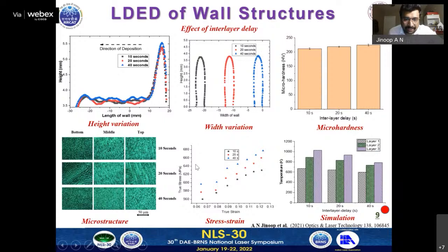And we could also see that the width value reduced slightly with an increase in the interlayer delay. The microstructural and mechanical properties show that the microstructure is relatively finer with an increase in interlayer delay, and the mechanical properties show an increasing trend with an increase in the interlayer delay. This is mainly because of the increase in the cooling rate that takes place with an increase in the interlayer delay. So to understand this process, we did numerical simulation again to predict the preheat temperature on the surface so that we can correlate with the results. We could see that with an increase in interlayer delay, the temperature of the preheat surface reduces, which results in the variation in the cooling rates and further results in the variation in microstructure and mechanical properties.